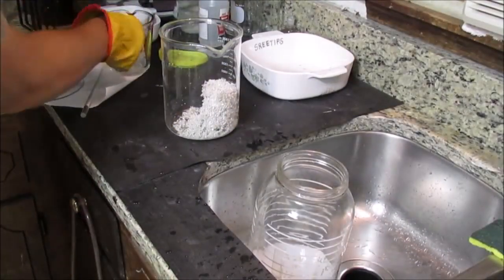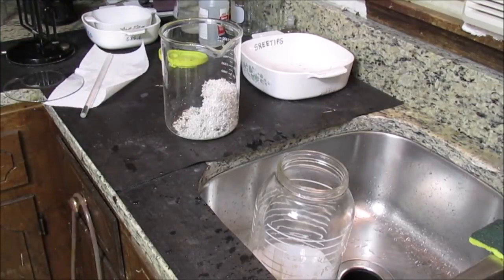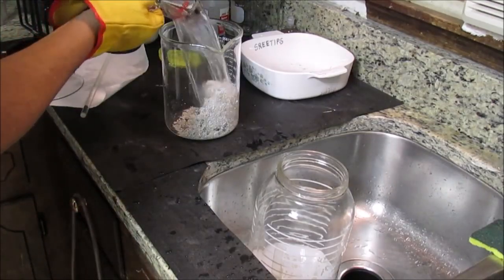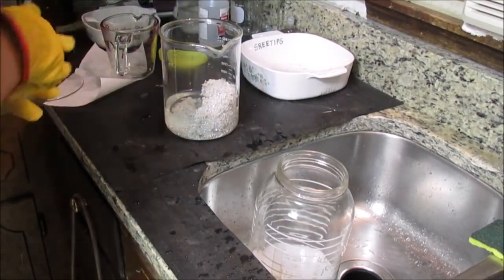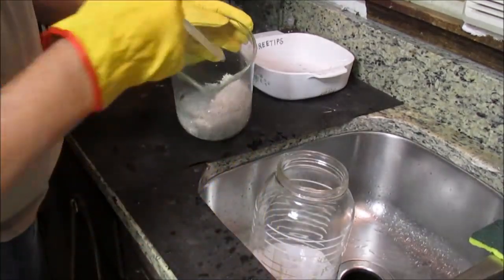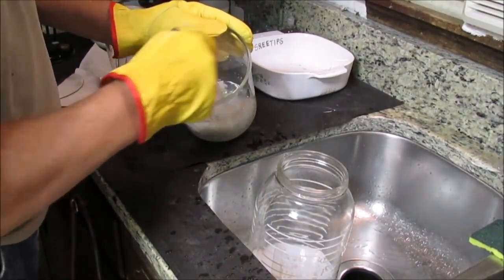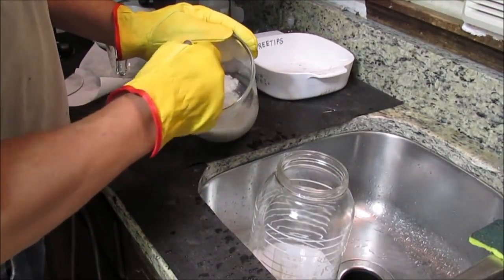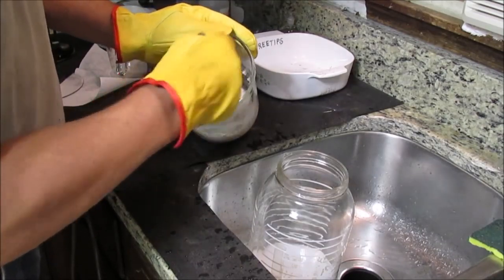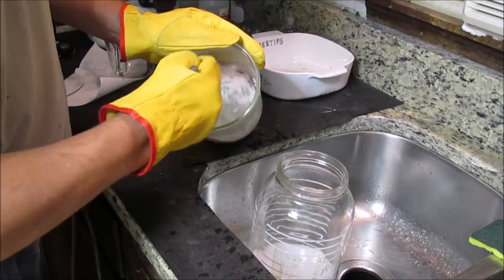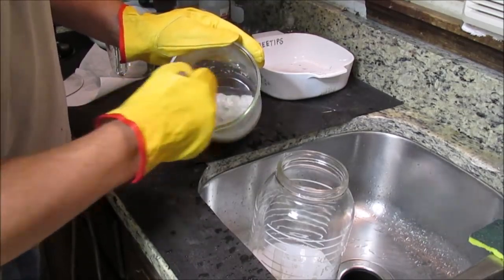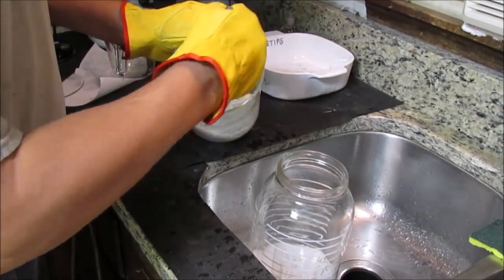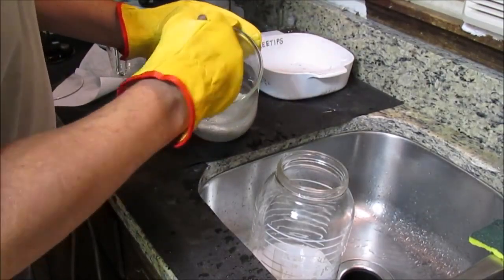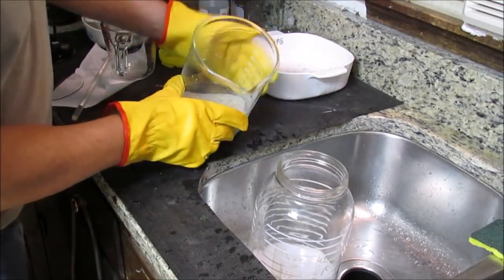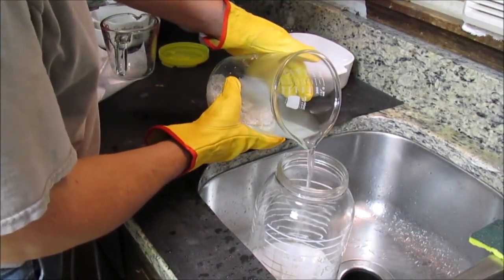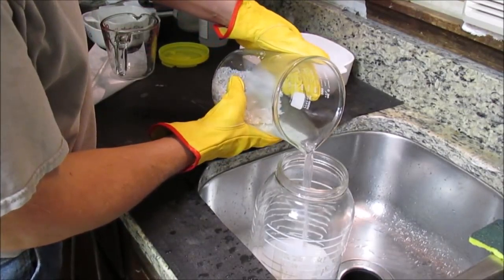Okay, the idea here is to rinse all the electrolyte off of the silver crystal. Just add some hot water to it, and then I take a thick glass rod and stir it up real good in there, making sure that as much of the electrolyte gets rinsed off as possible. And then I just add that to this jar down here because it's still got some silver in it, and I want to recover that silver out of this rinse water.